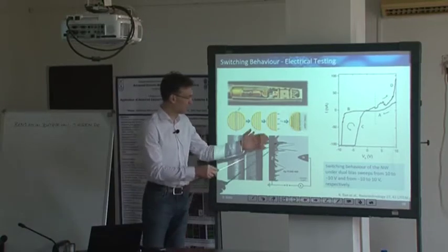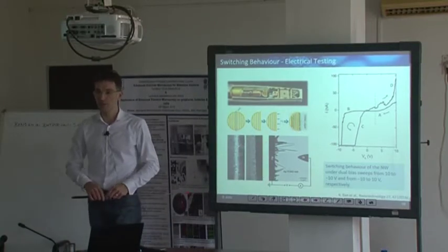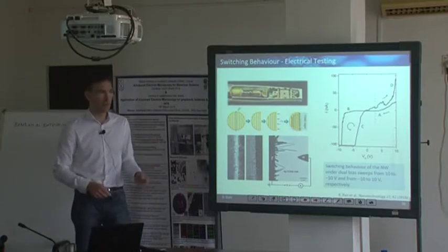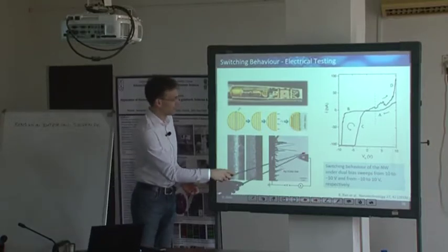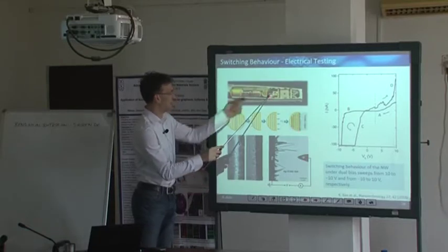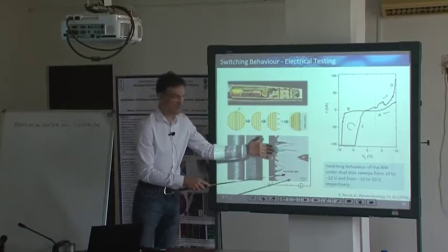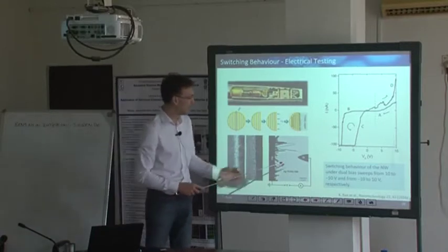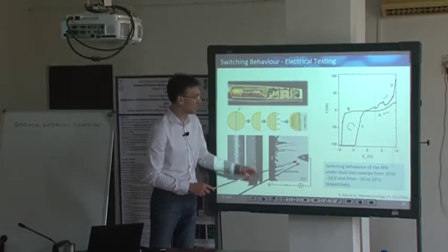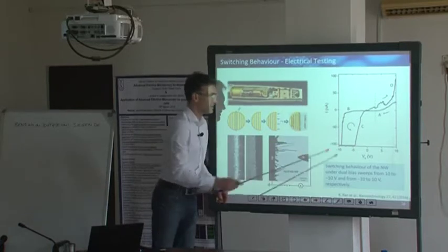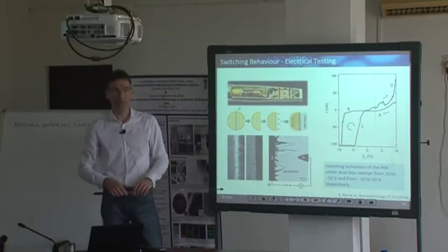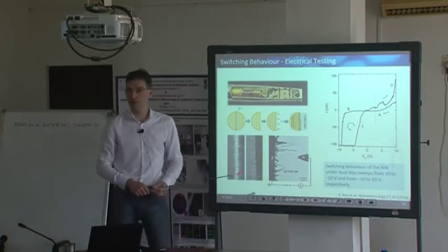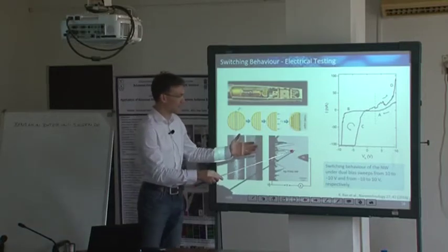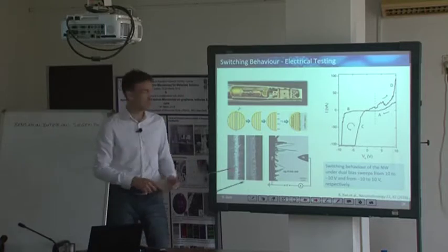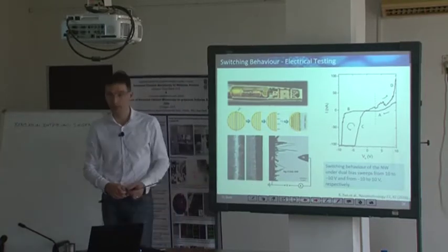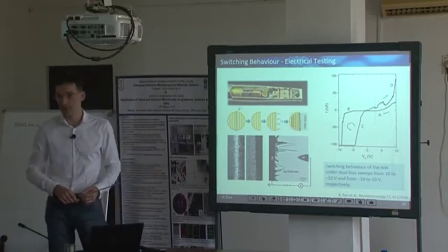The question was, people want to make use of those switching materials to realize circuits on a localized scale, and so we approached this metal tip on the right-hand side with our sample, by just moving our sample, and by contacting individual nanowires, we were able to demonstrate this hysteresis, so the switching behavior depending on the applied voltage. So you can do that on the localized scale. You can directly contact individual nanostructures. This is what you can do in a scanning electron microscope as well, just by using such nanomanipulators, for instance.